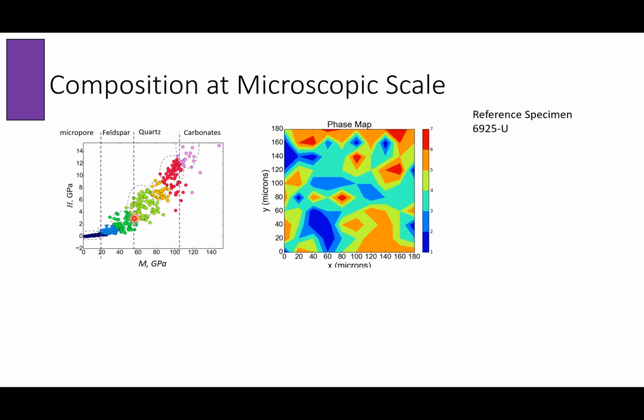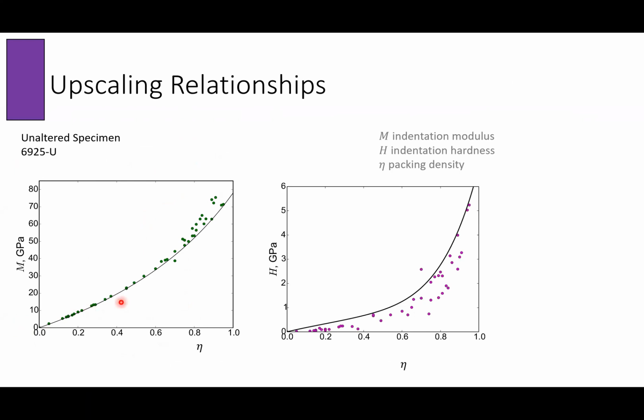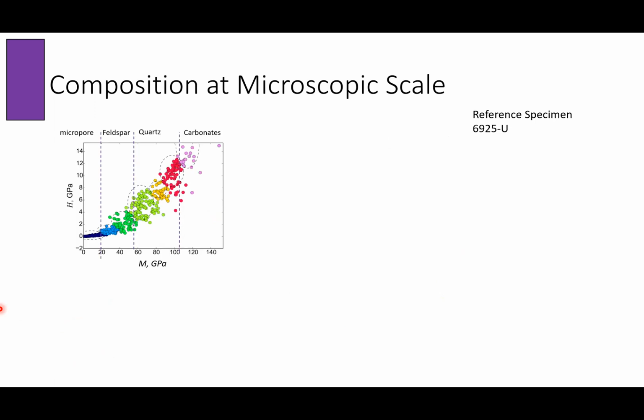And then for the feldspar, this is where I'm going to be using micromechanics to match it. I showed it here. I'm matching it to say my feldspar by definition is going to be nanoporous, so what's the level of my packing density on my feldspar? That way I have another threshold where I would say, at this level, this is going to be microporosity. I'm not saying that this is perfect, but that's the way I'm using to reduce the probability of those grain boundaries, and I will target primarily micropore, feldspar, quartz, and carbonates.